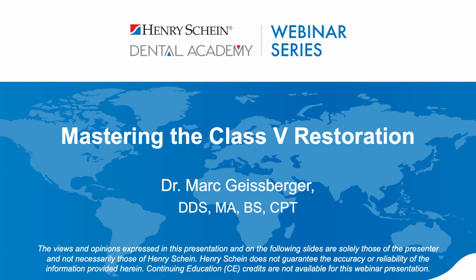Great. Just had one. How thick or thin is the layer of flowable? Well, the layer of flowable could be anything from, say, 0.5 millimeter to 1 millimeter to the entire restoration in flowable. With that said, remember, we are doing incremental layering to prevent massive shrinkage of the composite. So no more than 2 millimeters thick for that first layer. If you intend to do the entire thing in flowable, which is fine, you'd still want to keep that first layer to under 2 millimeters.